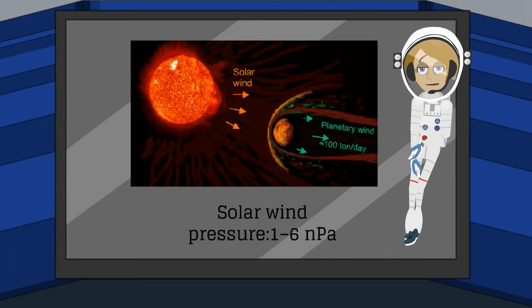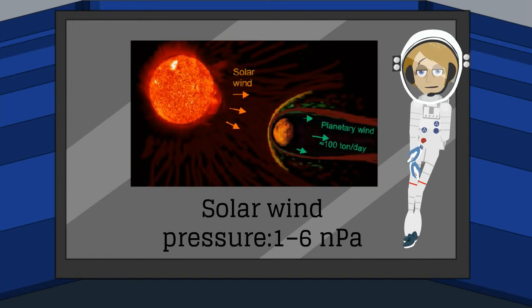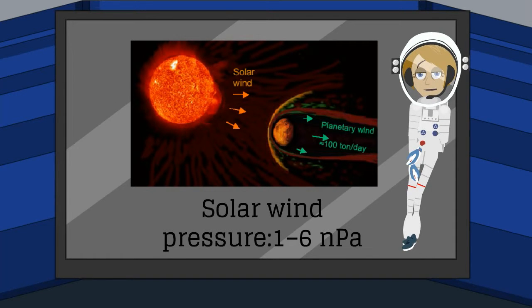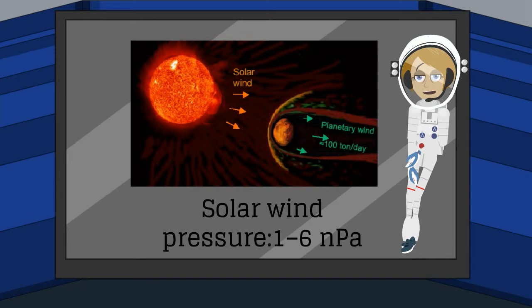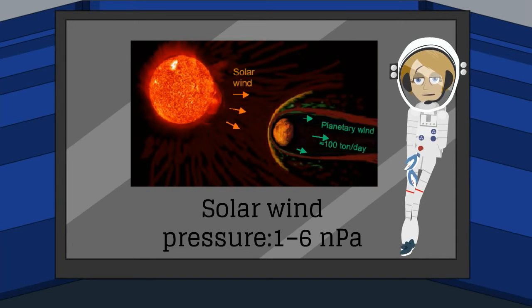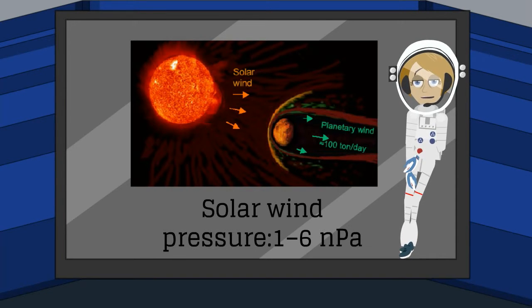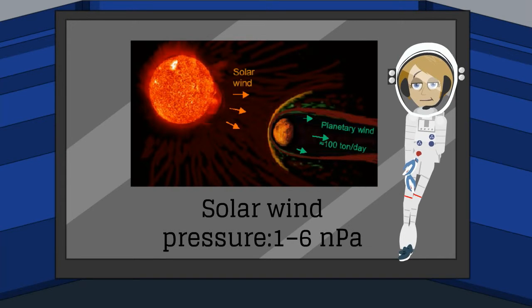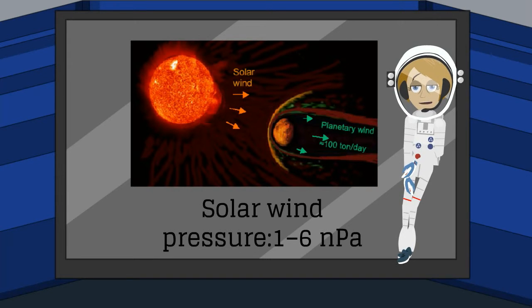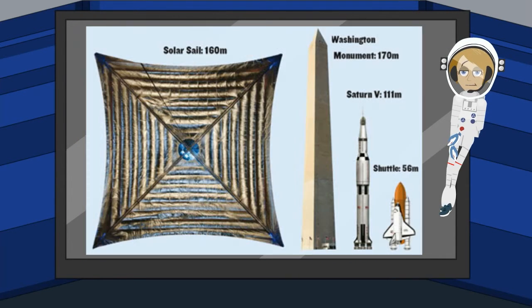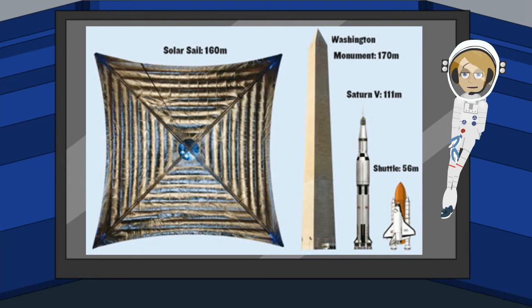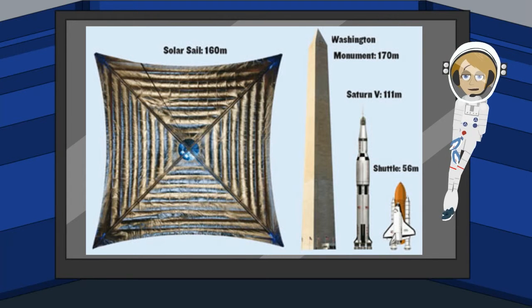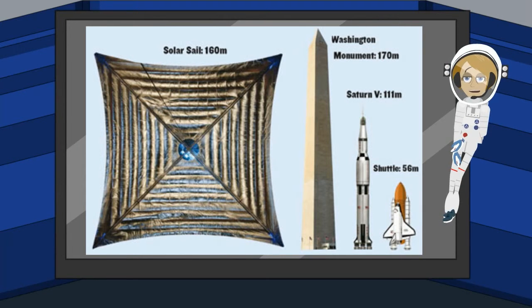Strength is necessary to withstand the solar wind pressure present in space. Kapton is able to maintain these properties over a temperature range of negative 269 to 400 degrees Celsius. This is a major issue with solar sails because exposure to direct solar radiation can cause much higher temperatures. When used in solar sails, the aluminum coating provides the reflective properties needed for movement. Kapton could potentially be pierced by meteoroids from time to time, but the effect on the sail's travel is minimal due to the large area.